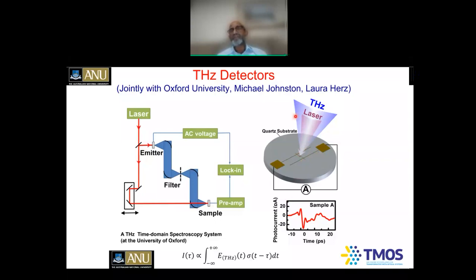We connect to an ammeter, we excite this nanowire with the laser pulse, and then you generate photocarriers and you come up with the terahertz pulse. The electric field of the terahertz pulse is the one which separates these carriers. You measure the photocurrent as a function of time. If you measure the current as a function of time, you can really extract the electric field of the terahertz pulse as a function of time and also measure the conductivity of the nanowire itself. And so in fact, initially we're exploring the electrical conductivity or electrical properties of these, terahertz spectroscopy of the nanowire ensembles.